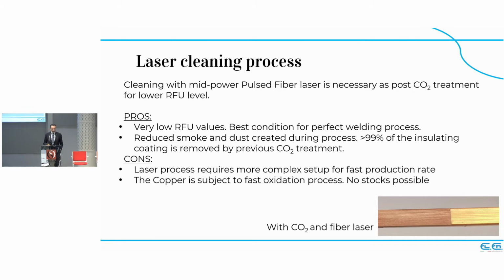The advantages are that we can reach very low RFU values. Low RFU values mean that no polymer is left on the surface, or almost none, and this allows a good welding process afterwards. In this way, we don't have too much production of smoke and dust because, as I said before, the dirty job is all done by the previous CO2 treatment. There are also disadvantages: in this case, we don't have the famous threshold I was mentioning before. So we have to fine-tune the process so that the powerful fiber laser is not too aggressive on the copper surface. And having a clean copper surface, it oxidizes much more quickly.